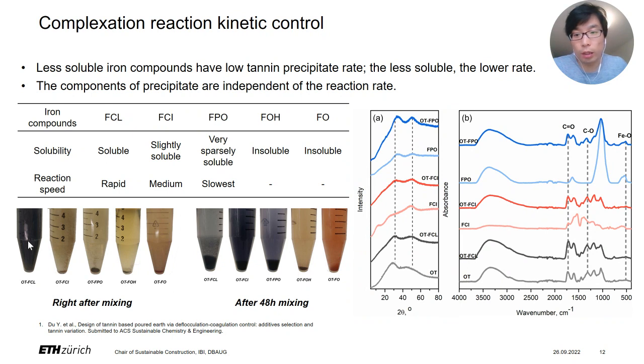As you can see here, in the picture showing here, right after the mixing, except the iron chloride, all the rest, we don't see any precipitate. The solution remains yellowish, but with the time going, we saw some precipitate form in the chloride, citrate one and the phosphate one, but not hydroxide and oxide one.